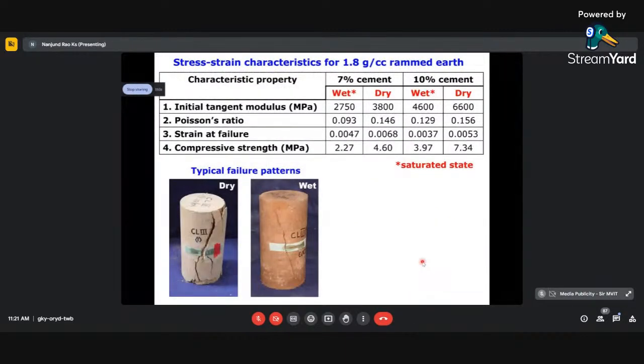Now, after having done this test, we have the numbers in this slide. For 7% cement, you see the initial tangent modulus was 2750 megapascal in the wet condition, and in the dry condition it is 3800. Wet means saturated: completely immerse the specimen in water for 2 days so that there is no further increase in the water that is absorbed. Then Poisson's ratio was around 0.1 in wet and in dry condition almost 0.15.